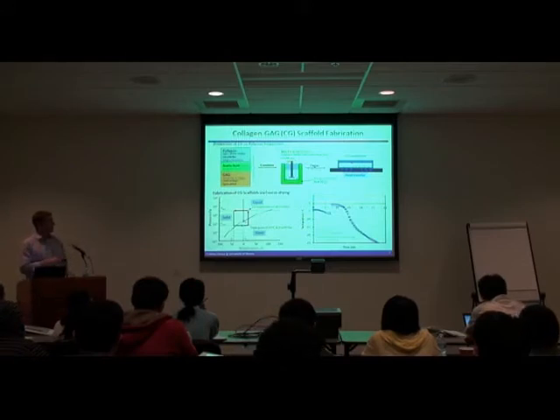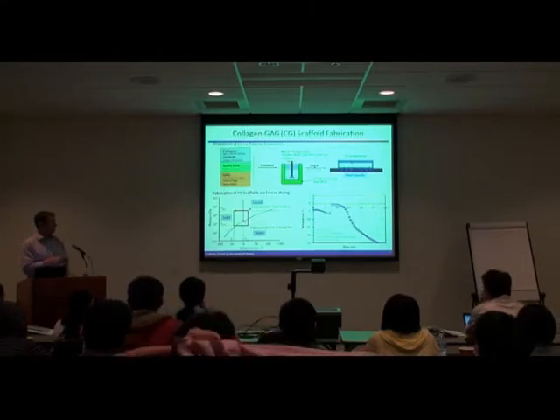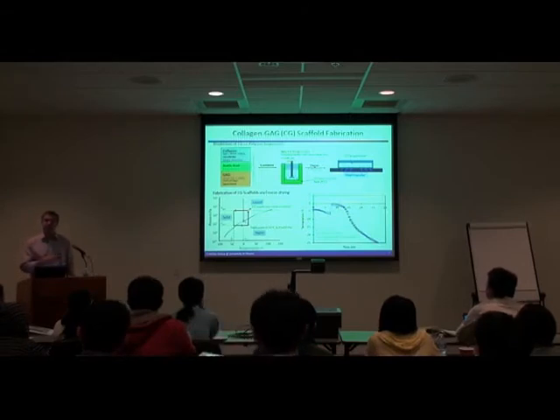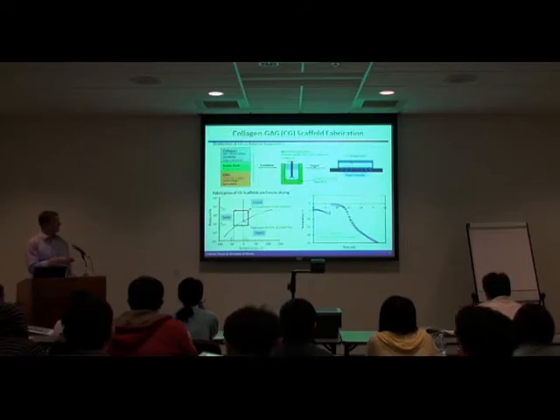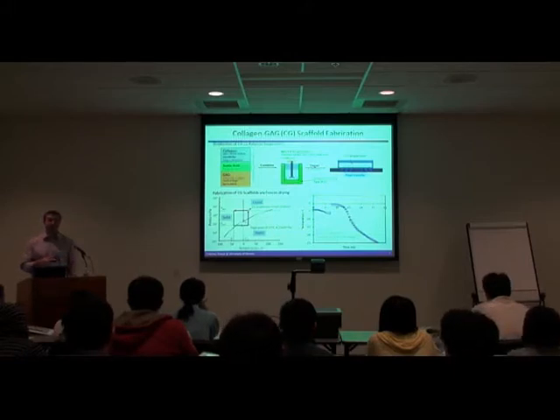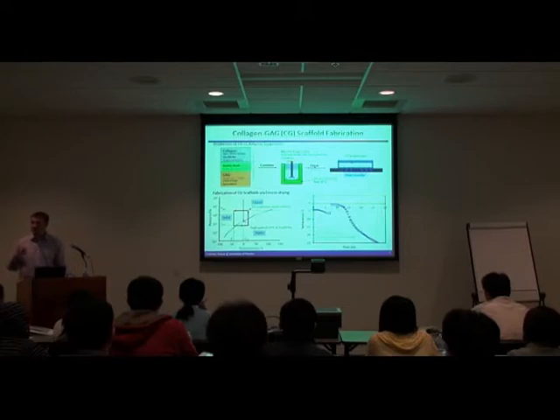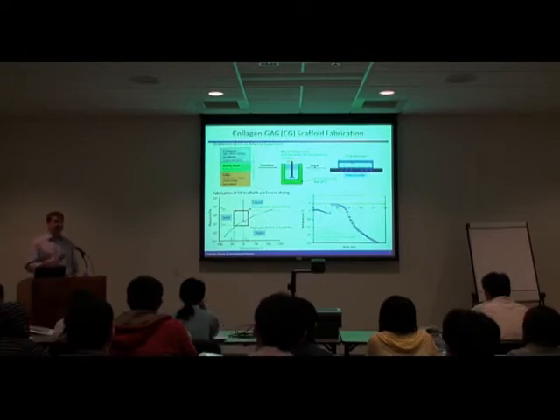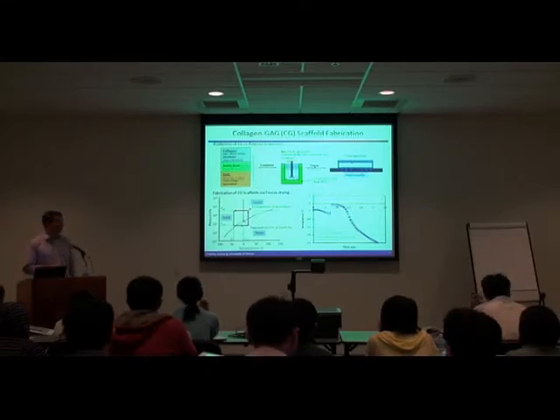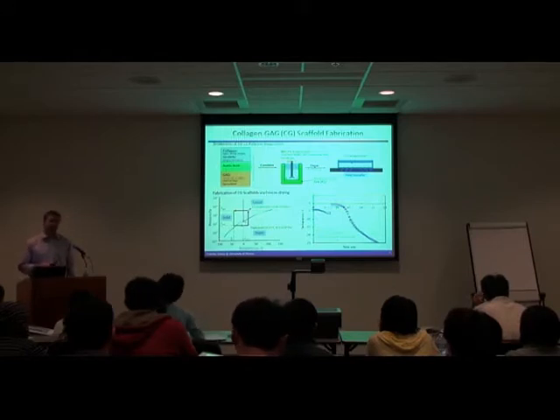The way freeze drying works is it utilizes the idea where you take your suspension in the liquid state and freeze it to get an interpenetrating network of ice crystals surrounded by the collagen and glycosaminoglycan content. Then by pulling a vacuum, you can sublimate out the ice crystals to form a pore structure. So the concept is that wherever you have an ice crystal that forms during solidification ends up being a pore in your final scaffold. By changing features around the solidification kinetics, in terms of the speed or the temperature or the directionality of solidification, you can change the size and the shape of the pores in quite a rigorous manner.